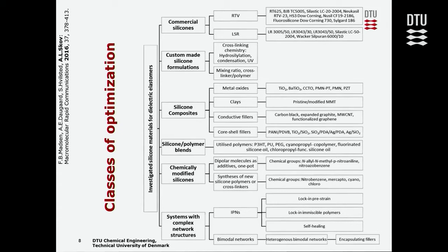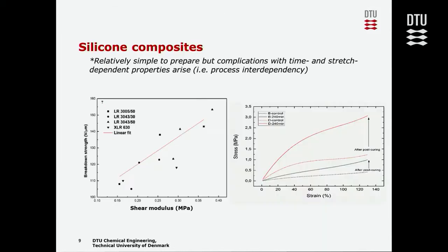Then there are others. We have grouped them into silicone composites, silicone polymer blends, chemically modified silicones, and systems with complex structures, and I'll just give one slide for each of them and tell about the good and bad things. So silicone composites, I think that's the most commonly used method. It's simply taking a commercially available silicone elastomer and mixing in metal oxides of various kinds, and then we have an improved dielectric permittivity, but usually the ratio of our dielectric permittivity over the Young's modulus is not improved. It's more or less constant.